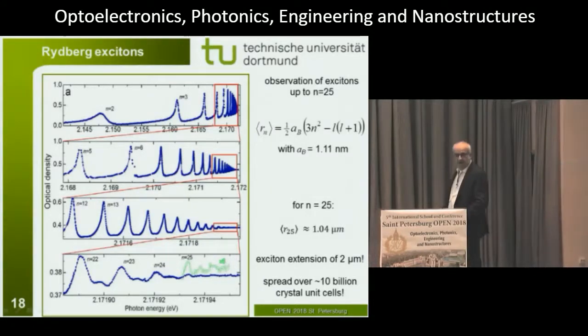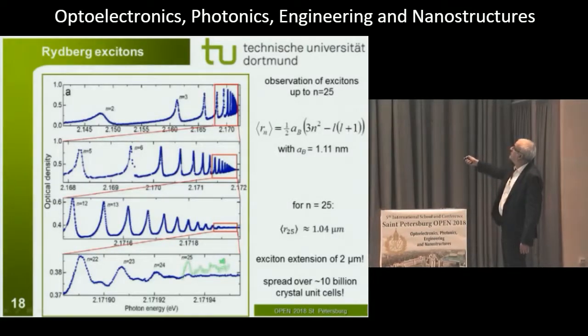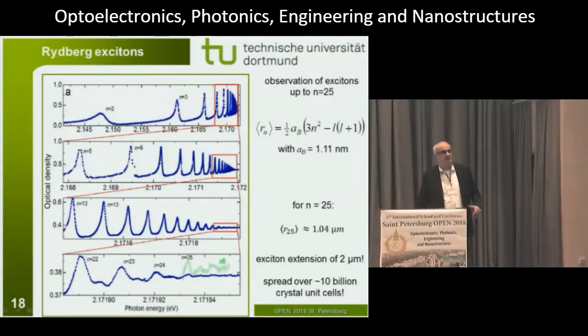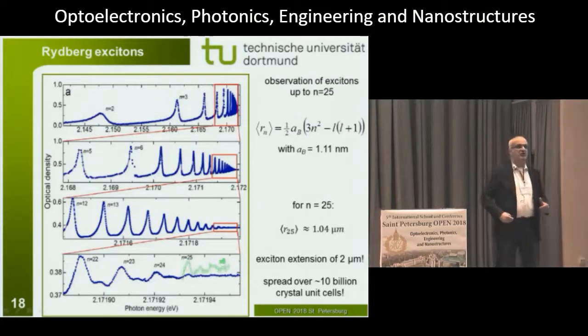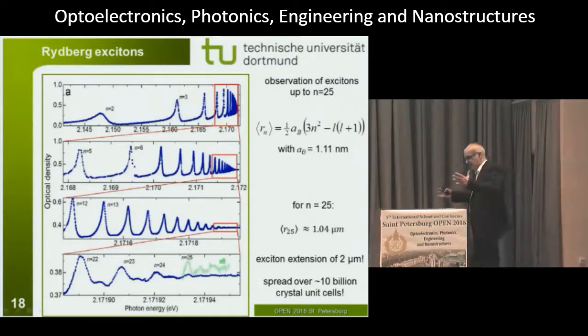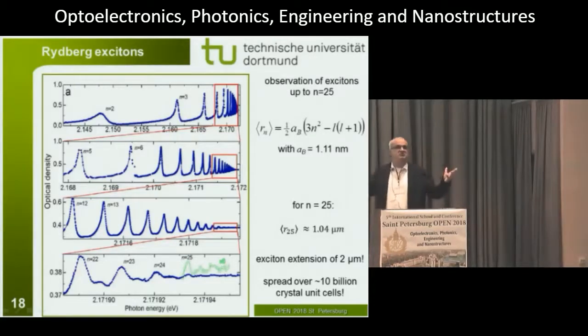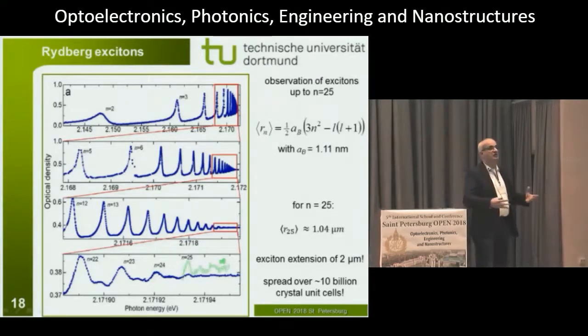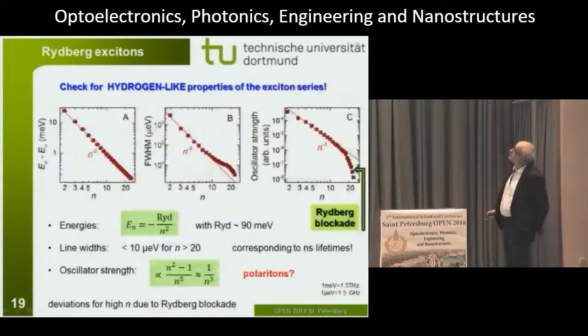Well, what plays in our favor is that the Bohr radius is 1.1 nanometer in our case. So if you plug in just the numbers and take the formula from the hydrogen atom for the average radius of an orbital with principal quantum number n, you find that these excitons have an average radius of 1 micrometer, so an extension of 2 micrometer, which means that they are extended over 10 billion crystal unit cells. So these are huge quantum objects moving in this crystal on a tremendous background of charges, but nevertheless they are stable.